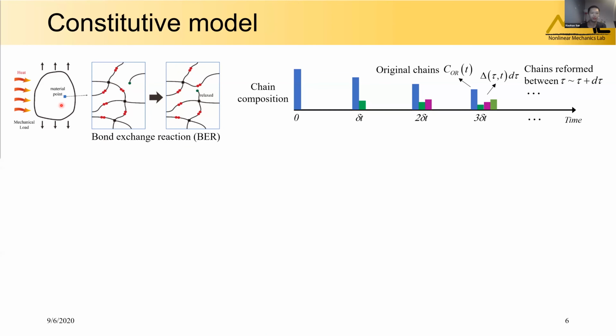Consider a material point subject to thermal and mechanical loading. The chains within this point can exchange through the BER. A basic assumption for BER is that the stress carried by a reacting chain will be relaxed after the BER, and the new polymer chain is born at a stress-free state, and it will start to accumulate deformation since its reforming state. So to obtain the total stress of this material point, we need to track the evolution of the chain composition, that is the original polymer chains and the reformed chains born at different times.